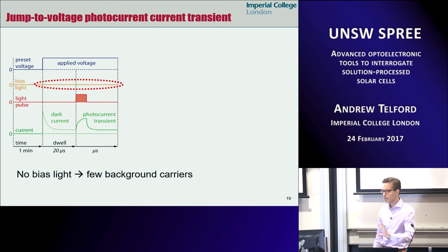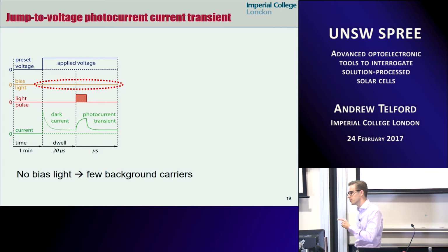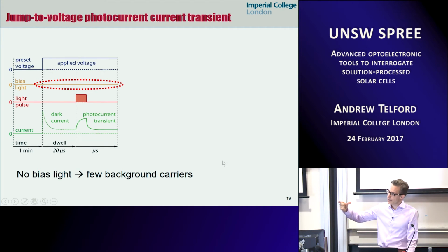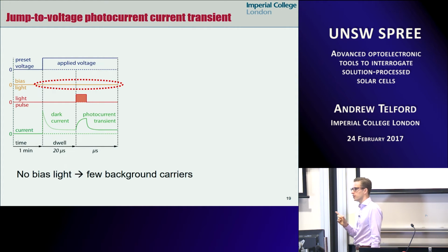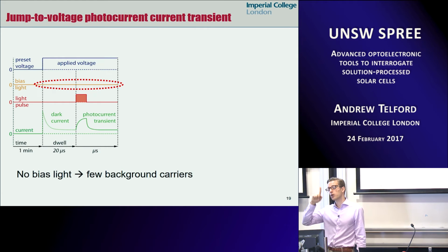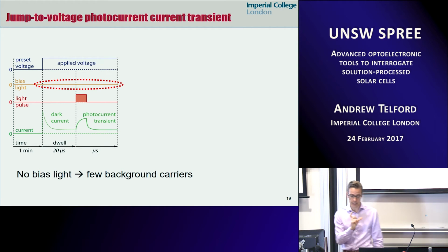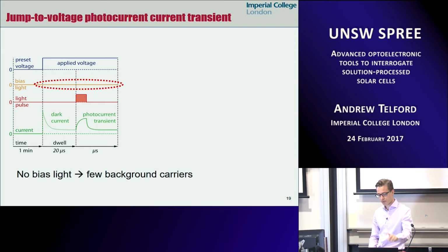Okay? And now we measure transient photocurrent, just because it's easier to measure photocurrent when you're applying a bias to the cell. And the signs will be reversed. So now if we do indeed have a reverse electric field in the device, we'll observe a positive transient photocurrent at early times. So what we do is that we switch the cell to open circuit with this forward bias, and then after a few microseconds we use a pulse and look at the transient response of the current.